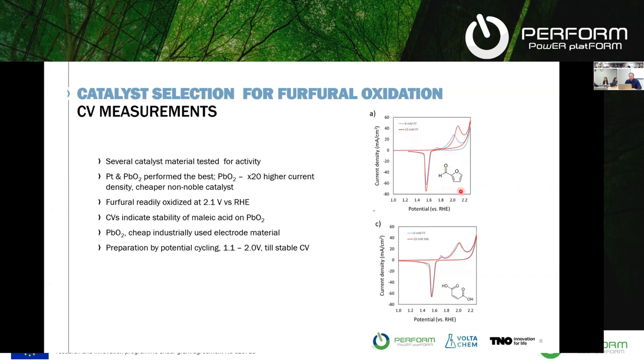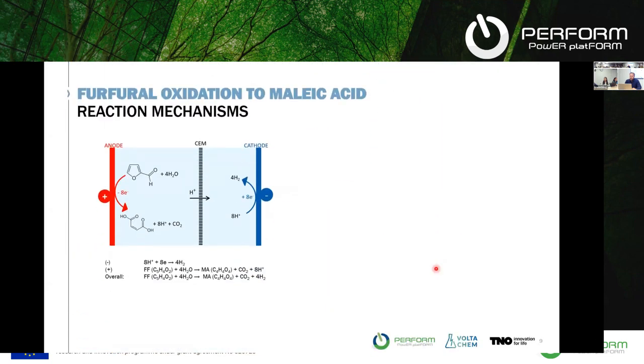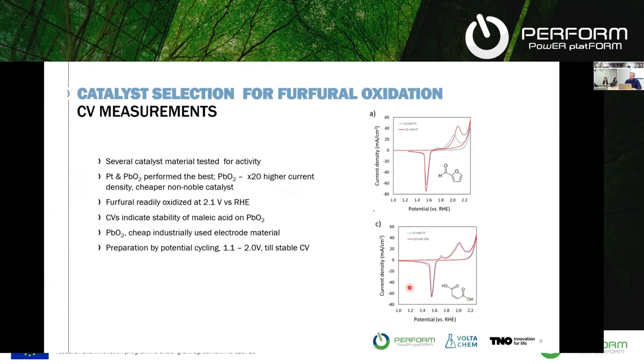One other thing to be careful about is that once you have chosen your catalyst, you need to make sure that your catalyst is not active at decomposing your product. So in this case, you look at the maleic acid as a product. If you check again the same voltammogram, when you have maleic acid in solution, you see now that the blue line and the red line are overlapped, meaning that your catalyst is not doing anything with the substrate or the product that you have produced.